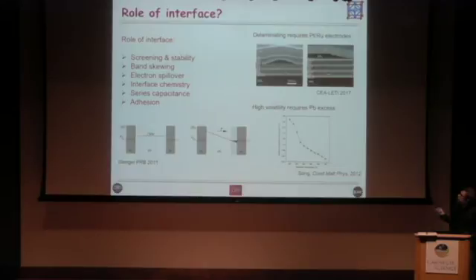Adhesion is illustrated here. A favorite electrode on CMOS-compatible capacitors could be platinum. But when you use platinum, in fact, that delaminates after a certain number of cycles. And so the solution is platinum with a thin ruthenium layer between the platinum and the PZT. And there's no delamination, and that's something we're working on quite recently.